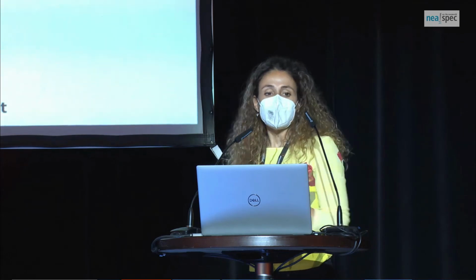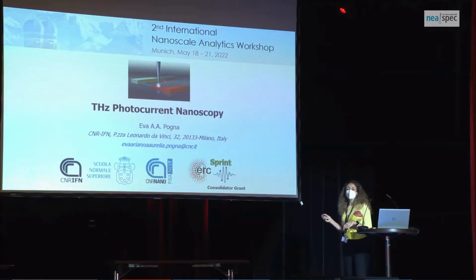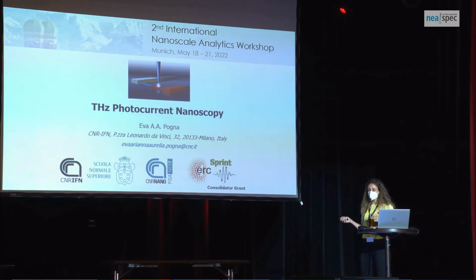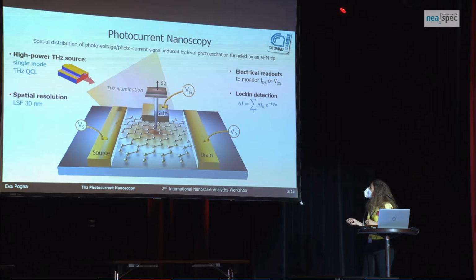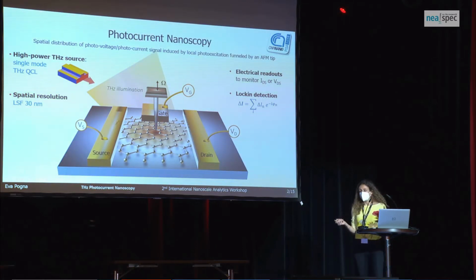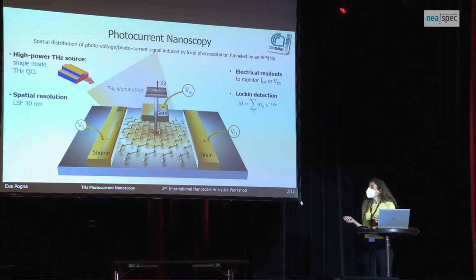I will challenge your attention with a little change of topic, because as my title suggests, I'm going to talk about photocurrent near-field microscopy in the terahertz range. This technique relies on the measurement of photocurrent and photovoltages when a sample is illuminated in the near field, in our case by terahertz radiation. To perform this type of measurement, you need a high-power source, which in our case consists of high-power, milliwatt power, terahertz quantum cascade lasers.